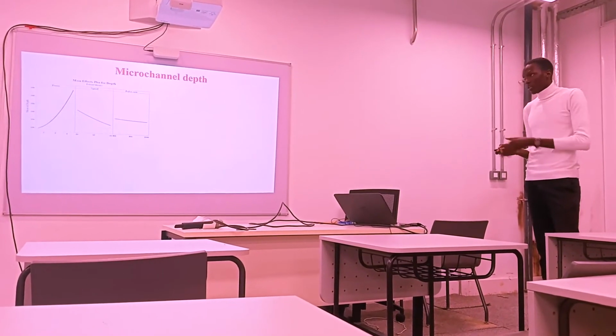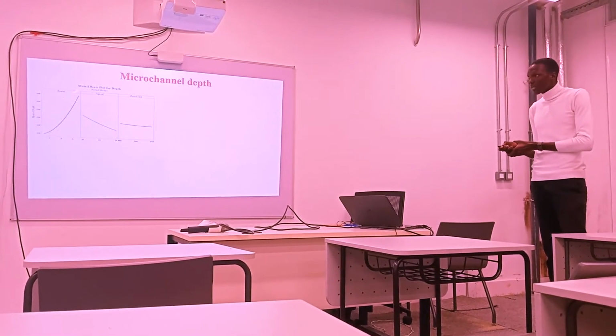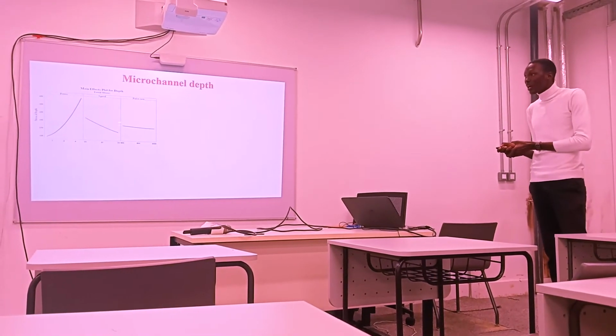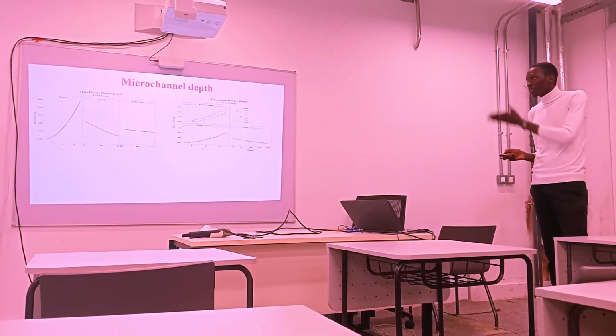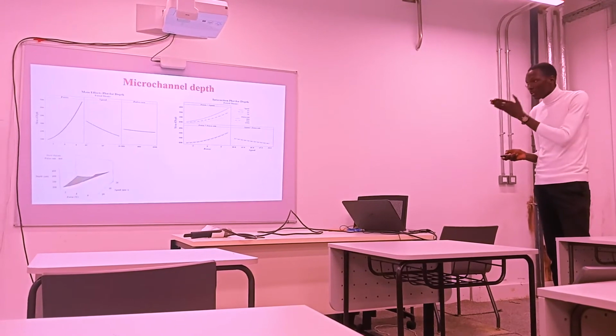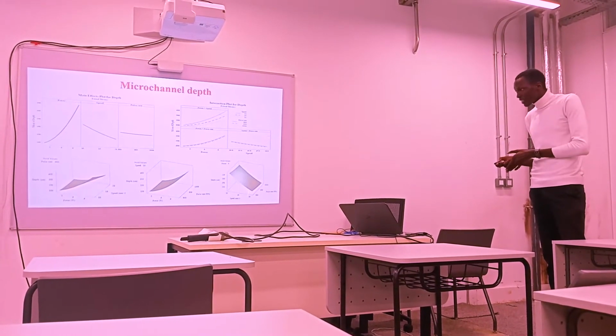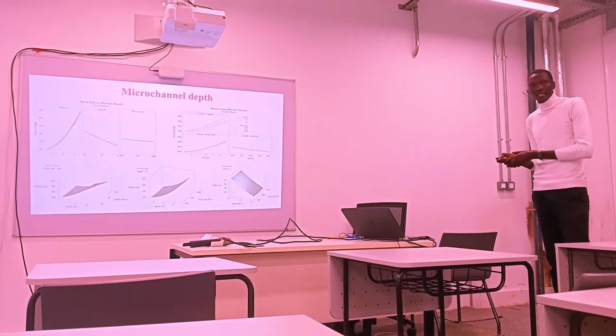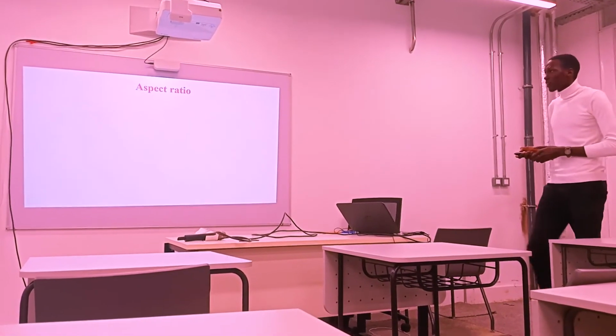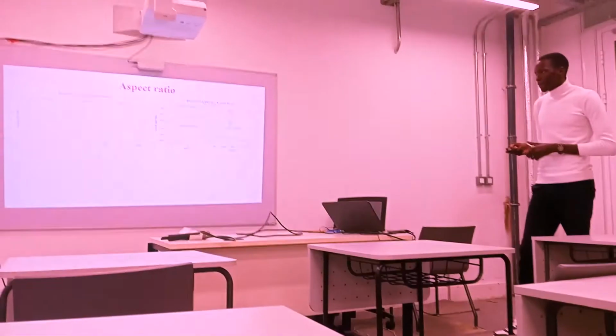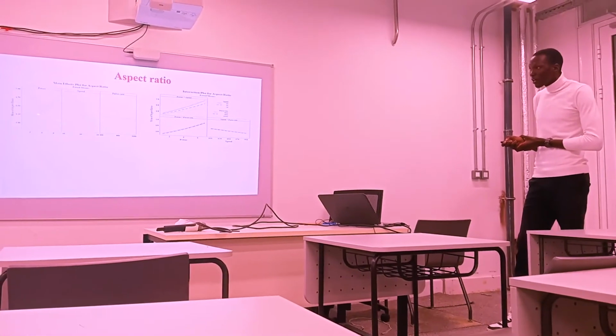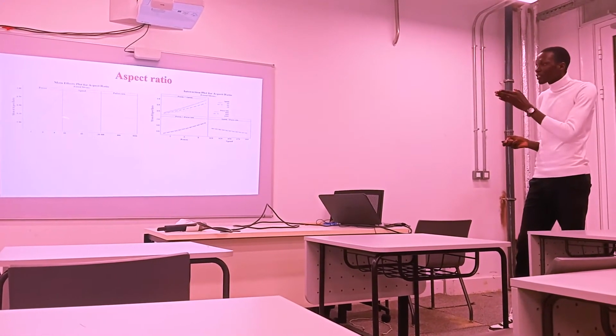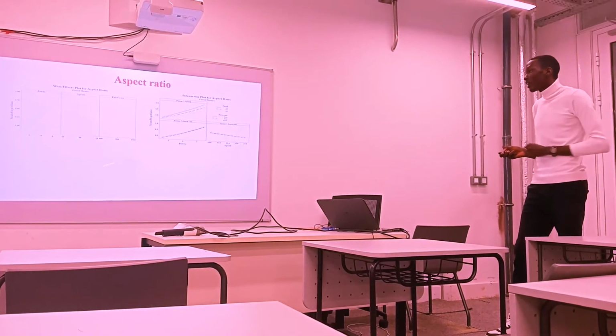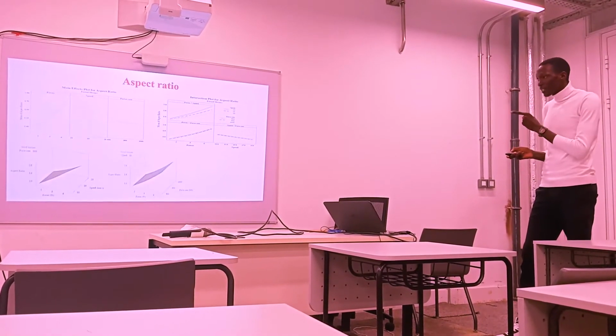Then, for depth, the same thing. It increases with the increase in power and decreases with the increase in speed and increase in pulse rate. The interaction plot and the surface plots, these figures, as I said before, communicate the same thing. And then the aspect ratio. The aspect ratio is a little tricky. It increases with the increase in power and also decreases with the increase in speed and the pulse rate. The same plots.